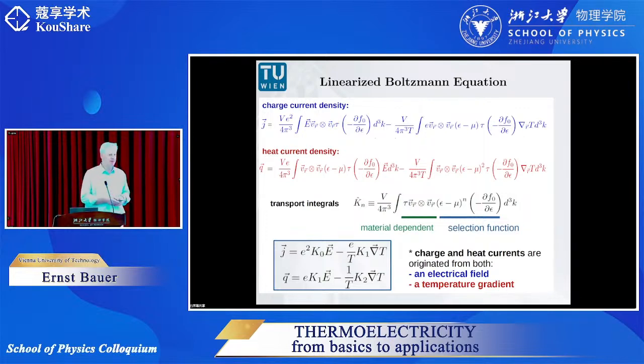A very important parameter here is the so-called relaxation time or the living time of a certain particle. And this relaxation time measures the time between collisions of the particles with other scattering centers, for example, impurities. And here you can already see if the relaxation time is small, that means one particle, one electron, can travel only a short distance between collisions, then the charge current density will be small as well. And in a material which is not perfect to 100%, you always have such scattering events, even at 0 temperature.